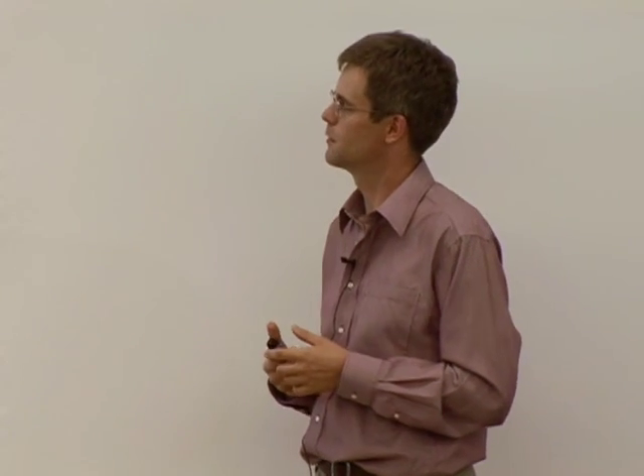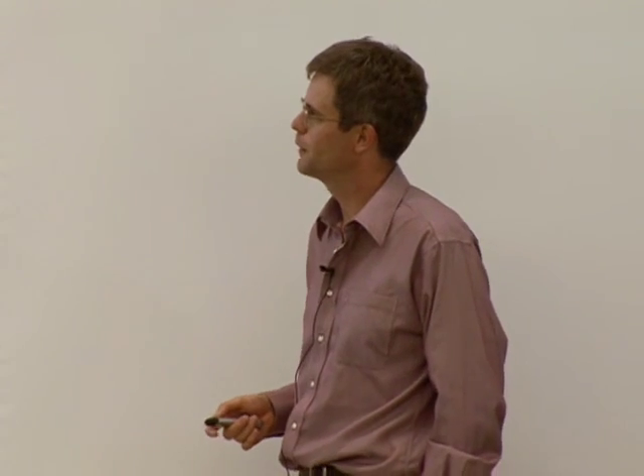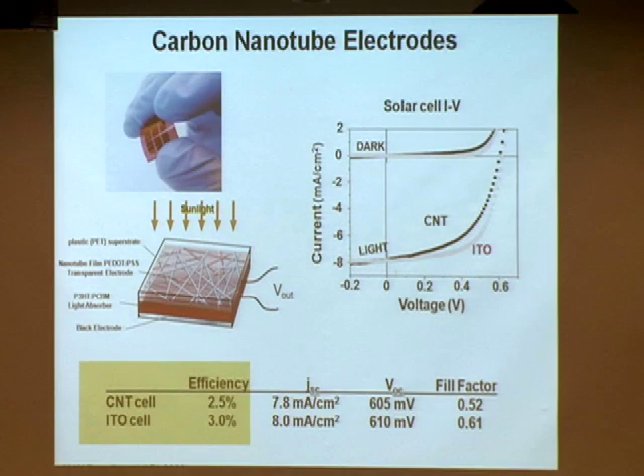And part of the problem there is ITO is deposited at 400 degrees, so the plastic substrates we would like to use can't handle the ITO deposition. So the solution that we propose here is using various kinds of nanotubes or nanowires instead of the ITO. So here you see a mesh of carbon nanotubes.